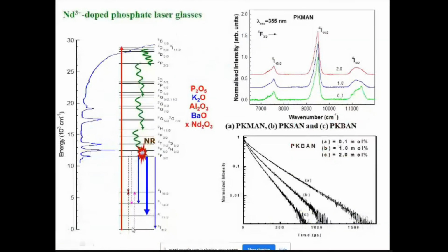And now just to see what I am telling here, this is the glass composition. Phosphate is the glass former. K2O, Al2O3, BaO are nothing but modifiers. Nd2O3 is the active ion. I am adding K2O, Al2O3, BaO in such a way that I may modify its physical properties such as density, mechanical properties, thermal properties, transparency. Keeping all those in mind, I am using different modifiers and changing the neodymium oxide. So depending upon the glass composition, non-radiative and radiative properties are going to vary. My intention is how best I can enhance the radiative properties, and by changing the composition I can do research in the glass and enhance the radiative properties.